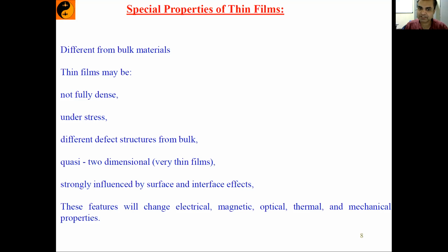Then we have different defect structure with respect to bulk. So again, defect is also a very crucial parameter which actually controls many of the properties. For instance, if you just look at titanium oxide or tin oxide, you will see that people generally talk very nicely that, okay, titanium oxide is a very good transparent conducting oxide. Tin oxide is a very good transparent conducting oxide. Similarly, zinc oxide. But how come it can be transparent and conducting together?